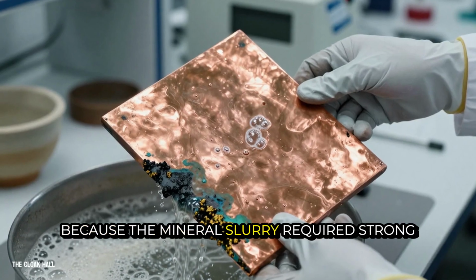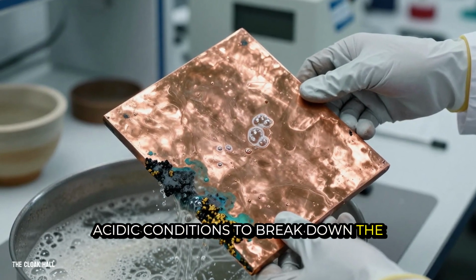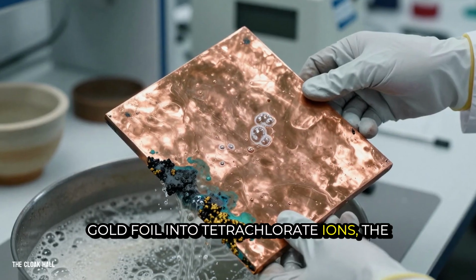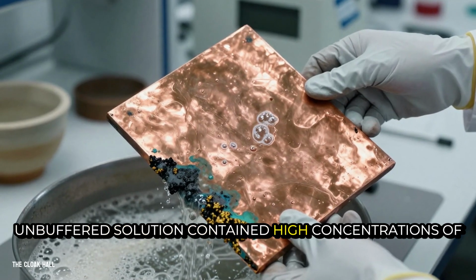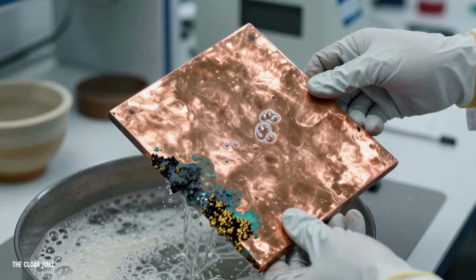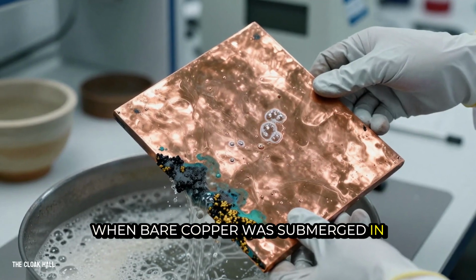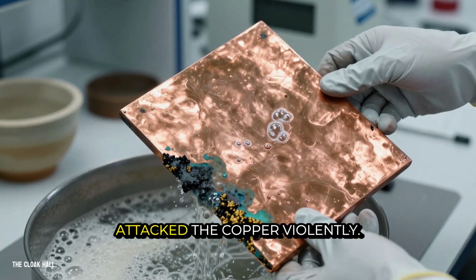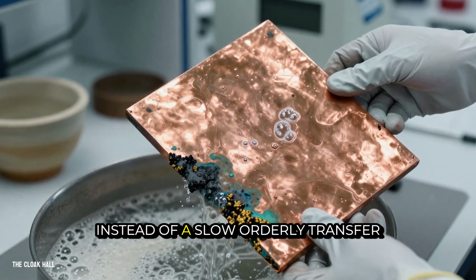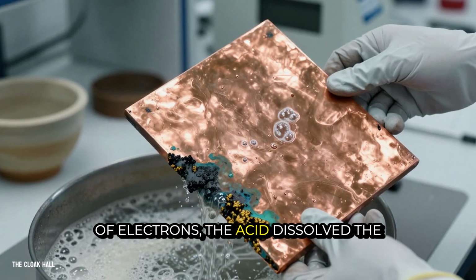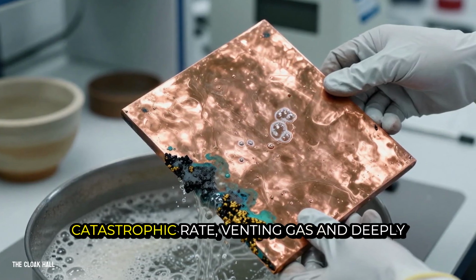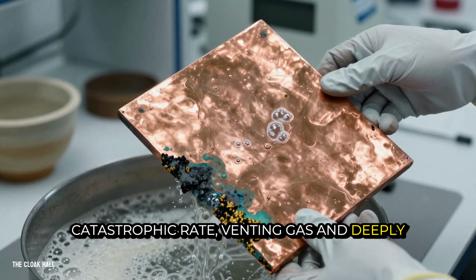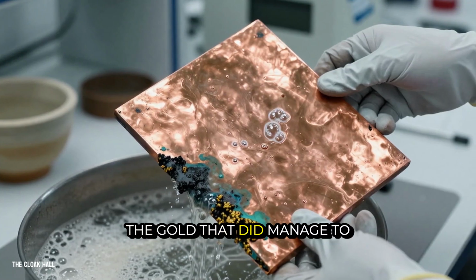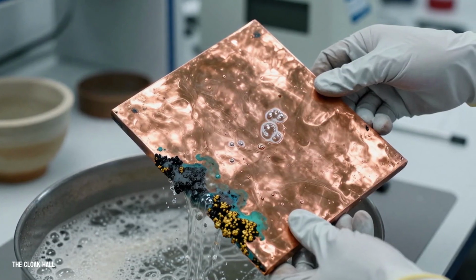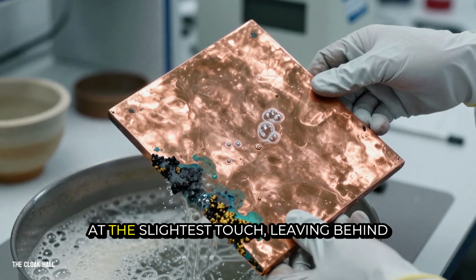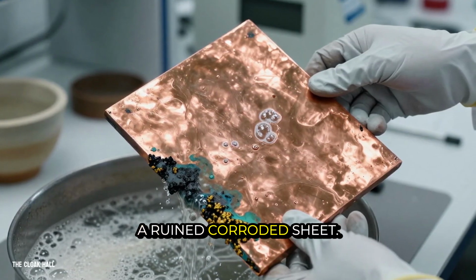Because the mineral slurry required strong acidic conditions to break down the gold foil into tetrachloroaurate ions, the unbuffered solution contained high concentrations of aggressive free acid. When bare copper was submerged in this strongly acidic bath, the acid attacked the copper violently. Instead of a slow, orderly transfer of electrons, the acid dissolved the copper into copper salts at a catastrophic rate, venting gas and deeply pitting the surface. The gold that did manage to precipitate came down as a coarse, dark, spongy sludge that sloughed off at the slightest touch, leaving behind a ruined, corroded sheet.